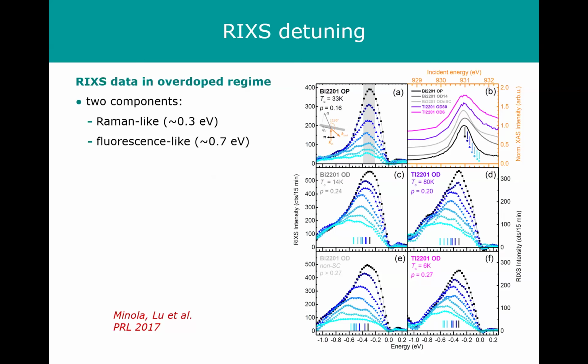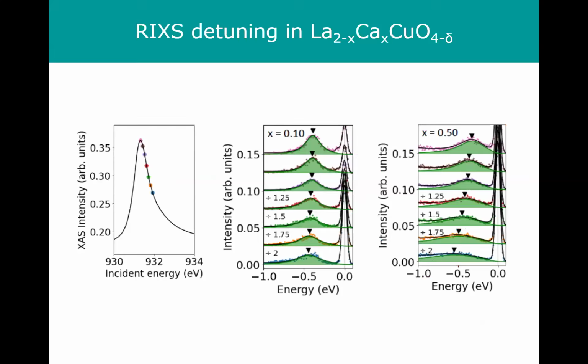Okay, so at low doping level, you see Raman-like response, and then as you go higher in doping, the spectrum becomes more and more single particle-like. And this is data that Sajina now took on the lanthanum calcium copper oxide, two different doping levels that show essentially the same effect. Right, so at low doping level, you see a peak position that's independent of photon energy. And then at higher doping level, you can actually analyze the data in terms of these two contributions, Raman-like and fluorescence-like, that we also found in the other cuprate systems.